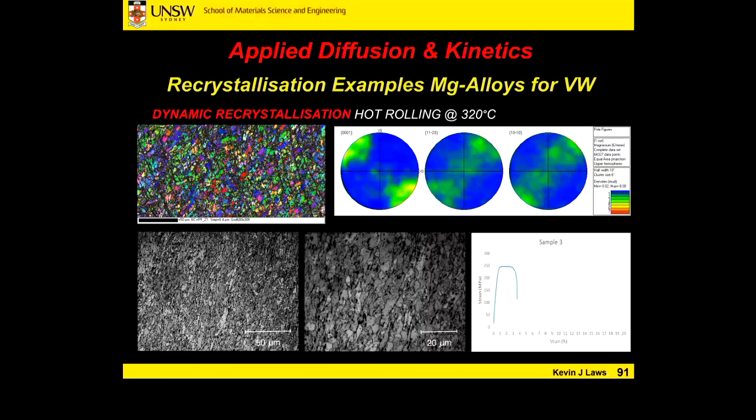So despite having a very high strength for a magnesium alloy, which is favourable, the ductility was terrible. 3%. You can't do much deformation, or this material can't take much load or fatigue or anything like that with only 3% ductility. So particularly for an automotive application, that's a fairly useless material. It's undergoing dynamic strain conditions all the time. So take note, that was at 320 degrees centigrade.